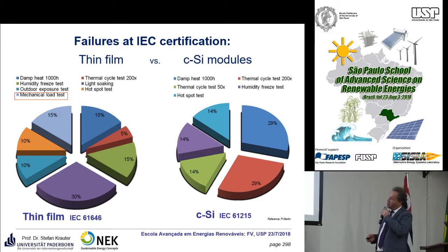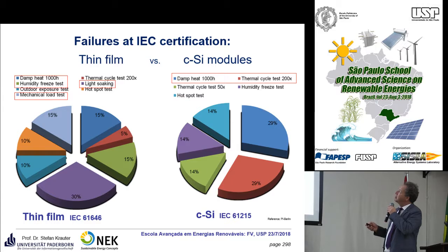These are some failures which occur frequently. For the thin films, most of the failures have been due to the mechanical load test because they are very large scale and sometimes they break. Light soaking also makes problems, and damp heat makes problems. For the crystalline modules, the most critical tests are the damp heat test and the thermal cycle test, 200 times.